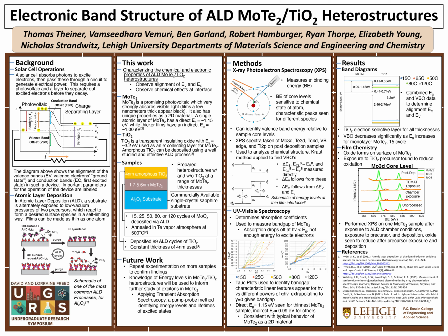So for my work, I work in a group that focuses on atomic layer deposition, or ALD. This is a process where you expose a substrate to two precursors alternately, and basically they react in a self-limiting way. I think this is summed up pretty well on the diagram I have on my poster, where you have TMA encounters the substrate. One layer adsorbs onto it, but then it leaves a bunch of methyl groups sticking out that other TMA molecules don't really want to interact with, so it's self-limiting in that way.